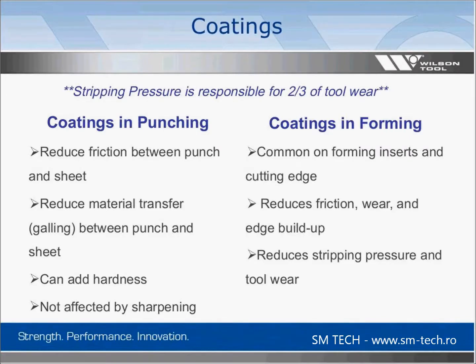As I said, two-thirds of all wear comes from the punch stripping out of the sheet. The use of coatings can greatly help reduce that stripping pressure and increase your tool life. Coatings are used in both punching and forming. In punching, they're used to reduce friction between the punch and the sheet, and reduce material transfer, you might know it as galling, between the punch and the sheet. Coatings can add hardness to the tool itself.